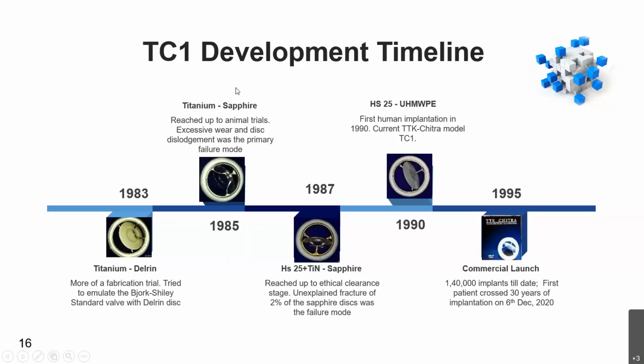So the first model came to the laboratory and went through some of our studies, and we found that this titanium is not up to the mark, in the sense that the wear rate of titanium is extremely high, and because of this the device will not last for the required service life. Incidentally, what we have to understand is that even though it's a small device with very few components, this device has to work for 2000 million cycles. 2000 million cycles is 2 billion cycles. That is the number of times a human heart beats during a span of 50 years.